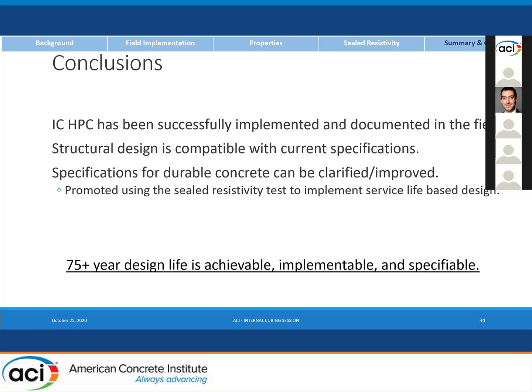Can you provide any suggestions of how to better meet the target about IC water? Some of the Indiana bridge decks had higher than 7% due to the way absorption was quantified when developing. So one of the approaches that perhaps was more conservative was that the DOT did not want the mixtures to be redesigned on the date of construction. And so we weren't able to use the absorption value as the actual absorption value and adjust proportions on the day. It was a meet or exceed.